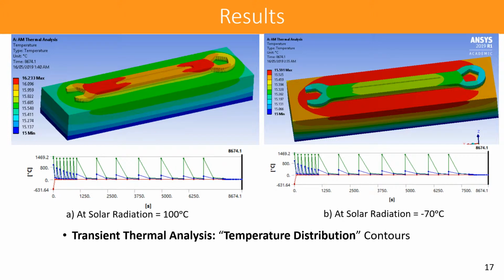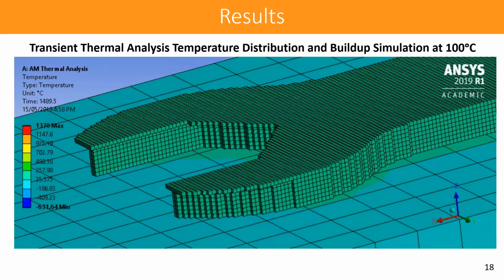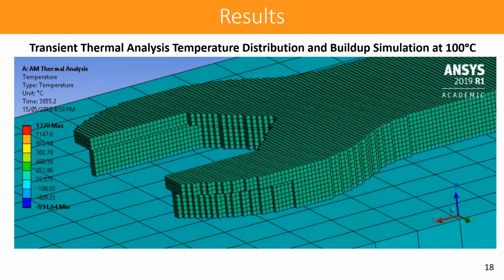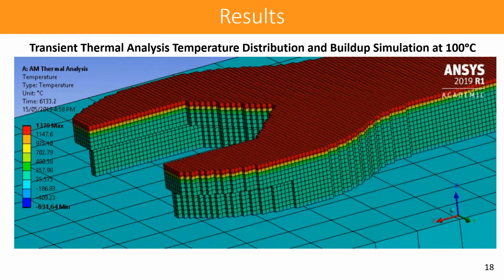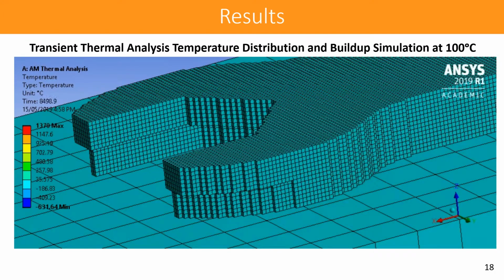From the temperature distribution contours for transient thermal analysis, the part on the left exposed to higher solar radiation has a slightly higher maximum temperature, whereas the figure on the right side shows that the temperature has seeped into the built part and the wrench no longer has the highest temperature, as the environment facilitates faster cooling. This close-up video of the transient thermal analysis shows more clearly how the element birth brings in layers at melting temperatures and each layer's cool-down process.